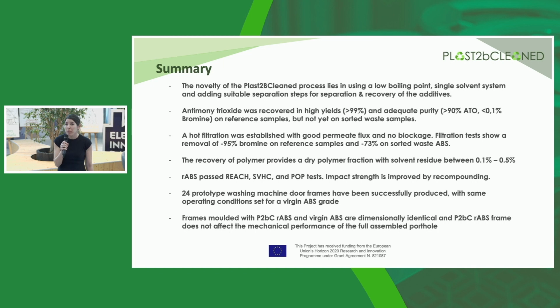So we managed to develop a process that relies on a low boiling single solvent and allows for the separation and recovery of polymer and additives. Antimony trioxide was recovered with high yields from reference material, and these results were unfortunately not achieved yet on sorted waste samples. With hot filtration, we managed to recover brominated flame retardants with high removal efficiency, above 95% on reference materials, a bit lower, 73%, on sorted waste ABS.